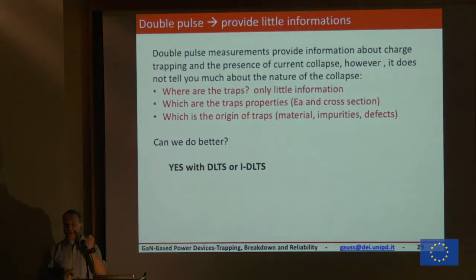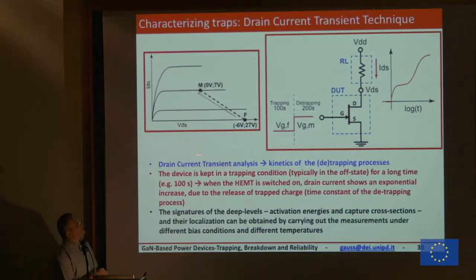Because with the two important pieces of information, activation energy and cross-section of the traps, we can really try to understand the nature of those traps. And this is what we have done, developing in our labs this drain current transient technique, that is a DLTS, deep level transient spectroscopy. With this, of course, this is a much more complicated measurement, it takes much more time, you have a lot of data to elaborate, but it provides you much more information.